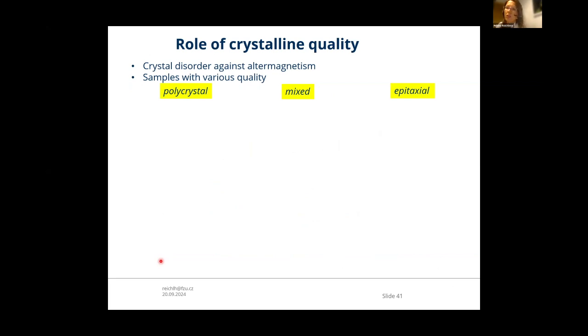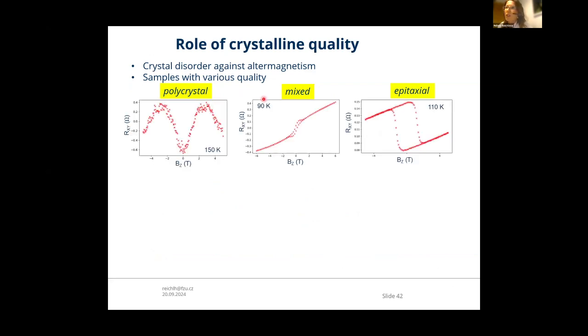I mentioned the role of crystallinity, right? In the polycrystalline film, we should lose this advantage of the sublattice allowing for the anomalous Hall effect. Indeed, we had samples of varying quality: polycrystalline, some mixed, and epitaxial films. In the polycrystalline sample, this is really raw data as we measure them, we observe no spontaneous signal, only some magnetoresistance probably coming from the misalignment of the contacts. In the samples of mixed quality, we start to see some anomalous Hall effect opening, and only in the samples which are really very high quality do we see the nice anomalous Hall effect.